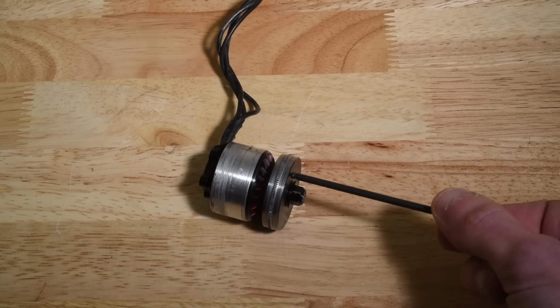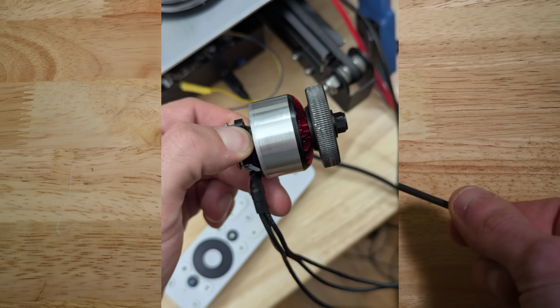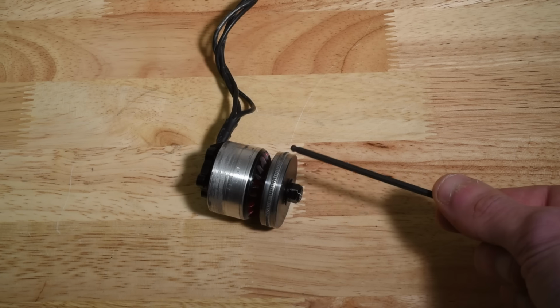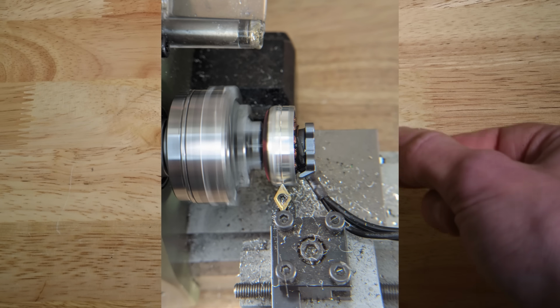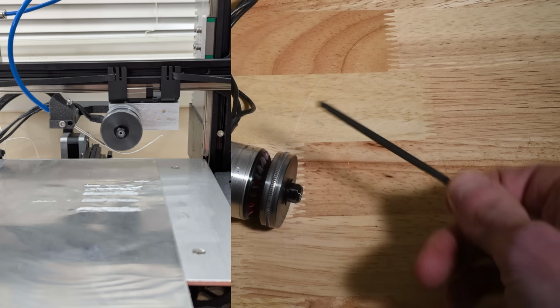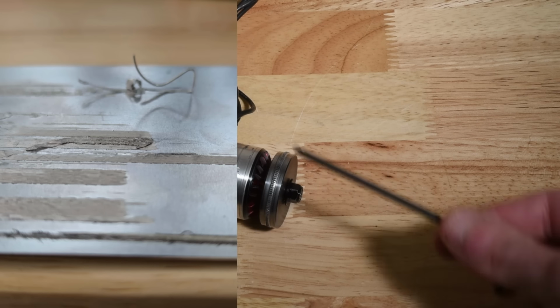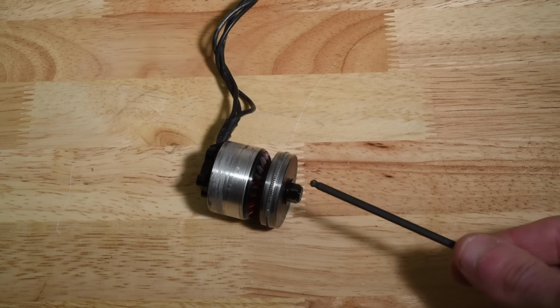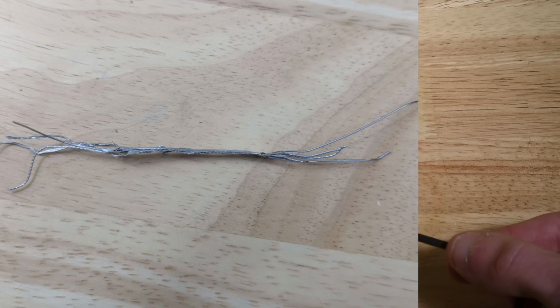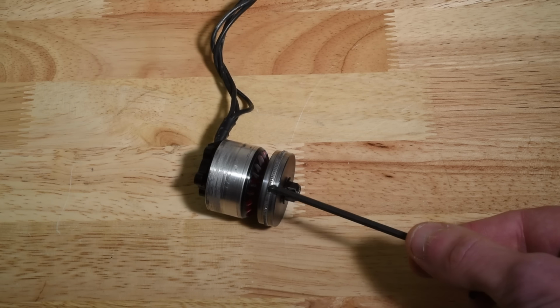We went to McMaster and we bought some M5 thumb screws that were made of A2 tool steel with black oxide finish, and had a knurled edge, and were just a little bit bigger in diameter than the turned down bell of the BLDC motors. And that worked great. We got reasonably long deposits of up to 10, 15, 20 layers, and they had thickness and could be removed from the build plate and handled. That gave us some hope.